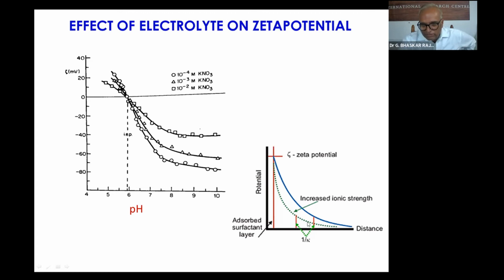You can exactly estimate how, by increasing the electrolyte concentration, the electrical double layer will get condensed. See, in all these operations we are looking at a surface of a few nanometers, which means we are exactly looking at the surface reactions. What is exactly happening at the surface of the particle or the material on the surface of the particles. Zeta potential, even though it doesn't directly reflect the surface of the particle, gives, near the surface, a few nanometers away from it, a clear-cut picture of what is happening at the interface level.